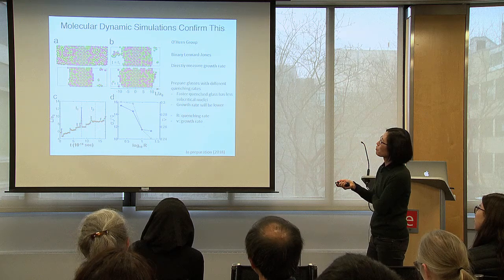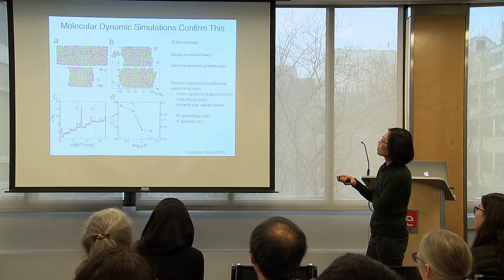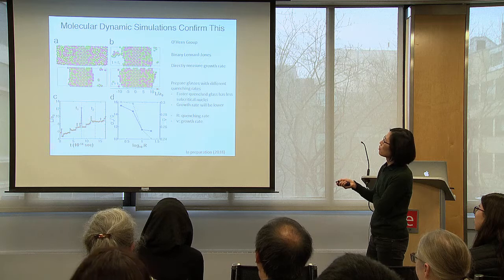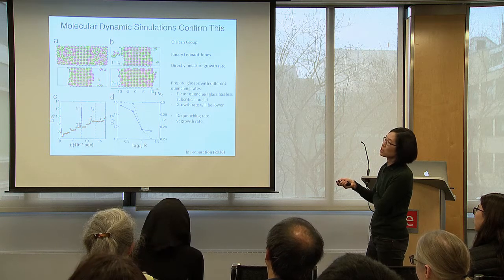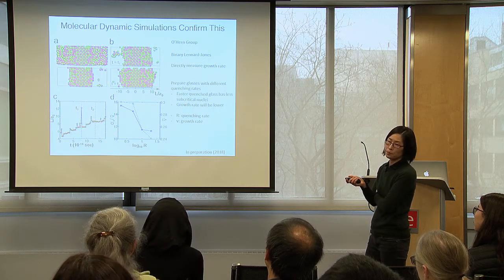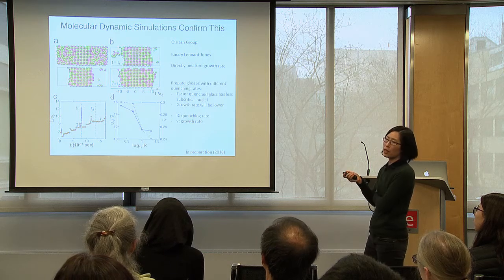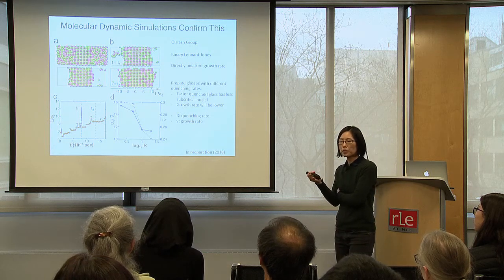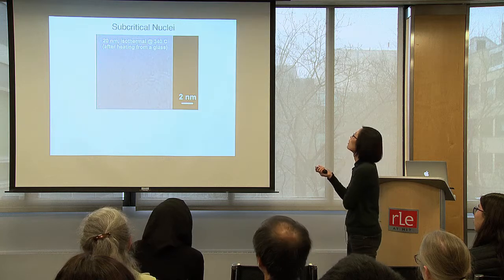So R is the quenching rate. The faster the quenching rate, the slower the mean growth rate, and also the lower the fluctuations that we saw in the growth rate. This is, of course, simple binary Lennard-Jones, but I think it can capture some essence of what we see.